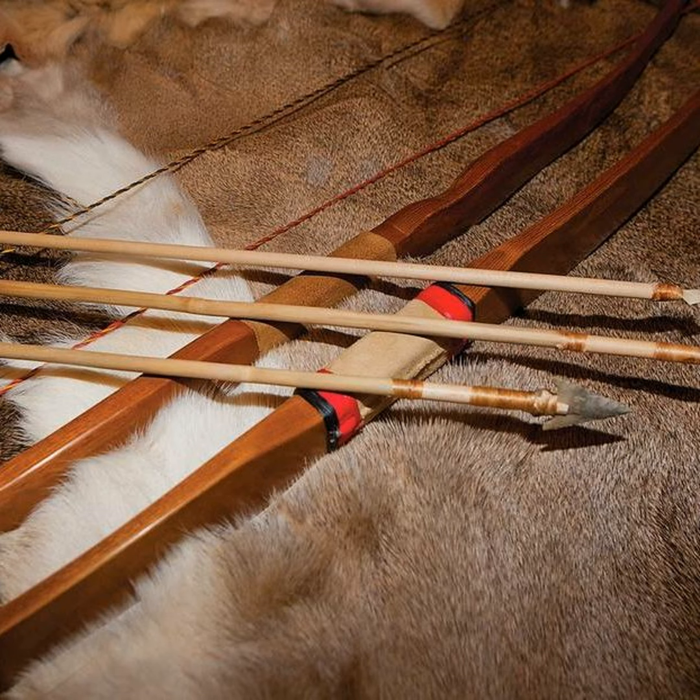So when we continue to look at various species here, if I continue to look at the prime examples, let's take a look at European yew. In this case, we have a modulus of rupture of about 15,000 pounds per square inch and an elastic modulus, MOE, of 1.3 million. So those numbers are lower than Osage orange, but a similar ratio there, 1.5 to essentially 1.3. So very, very close. Again, almost a 1-to-1 ratio. So therein lies the secret.